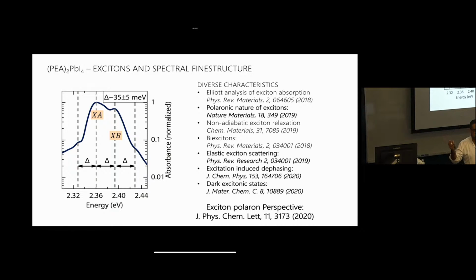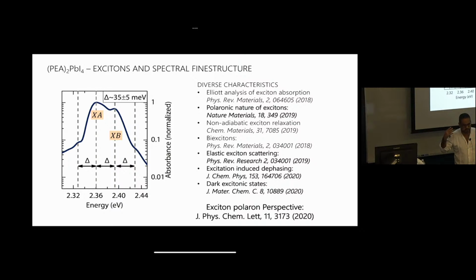And then all of the interactions, all of the Coulomb correlations between an electron and a hole, contain all of the couplings of each carrier to the lattice, so that the quasi-particle is really a composite exciton and polaron, a so-called exciton-polaron. And so the exciton-polaron hypothesis was first formulated in our minds, and we thought, well, what if you have diverse correlations between, let's say, polaron-polaron, untrapped carrier-polaron, untrapped carrier-carrier. Now that's a simplistic way of looking at it, but that was the idea.